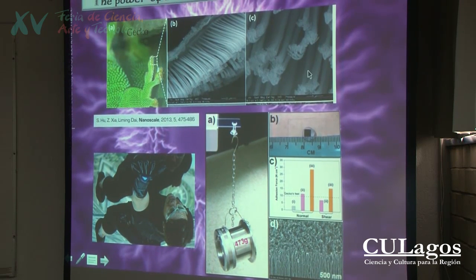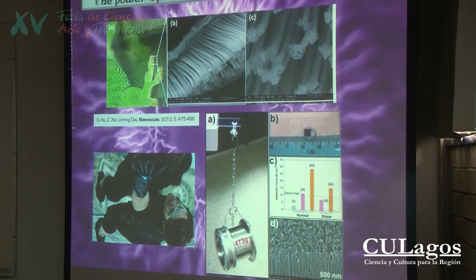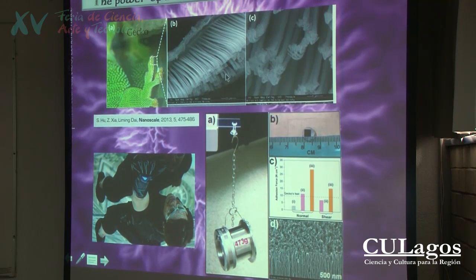And the interest of this is that the surface of contact between the fingers of the lizard and the surface he wants to climb is huge, because there's a division of the matter which is improving the surface of contact. So this is adhesion based on van der Waals interaction. I don't know if you know that. The adhesion can be chemical adhesion if you create chemical bondings between the different surfaces, or simple non-covalent bonding. So in this case, it's simple contact forces that will allow the lizard to climb.